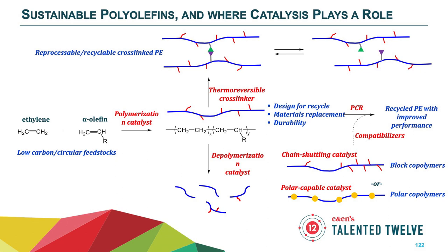However, in collaboration with Northwestern University, we're developing thermoreversible cross-linking strategies whereby you have a cross-linked polymer that has improved mechanical or creep resistance, and then you can apply an external stimulus, such as temperature, and break up those cross-links. Once you break up those cross-links, you can reprocess and recycle that material and reuse it for a different application.